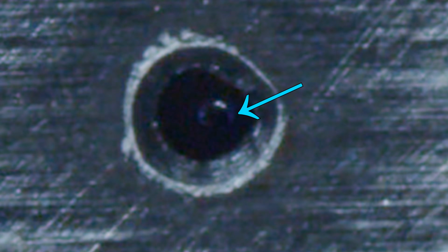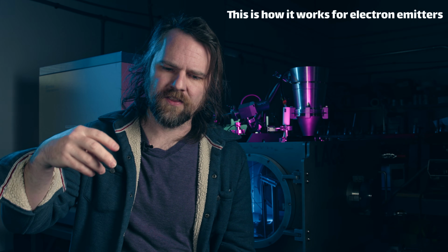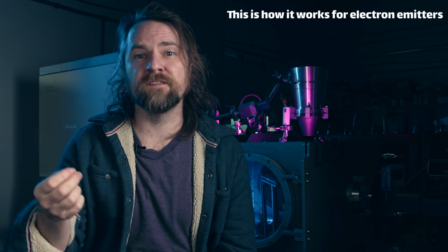I tried to reduce the aperture size, but this brought back some arcs and shorting, and I wasn't able to get it stable at a smaller aperture. I decided I needed a sharper tip than I could get with the capillary tubes. I thought sharper tips would reduce the onset voltage because, the sharper you get it, the more intense the field is at that location. I later learned this really wasn't the case for ion field emission, but oh well, that's what I did at the time.